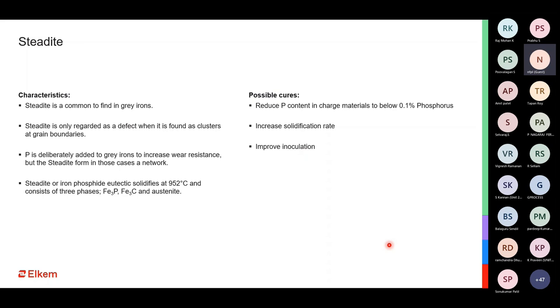Like I said in the previous slide, heat treatment does help in resolving the carbide issues. But because these phosphide eutectics solidify at 950 degrees also, heat treatment cannot get rid of the steadites. So steadite becomes a much bigger problem and a headache for a foundryman compared to carbides.